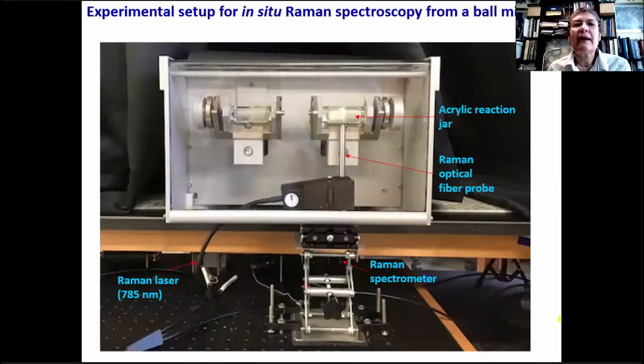So this is a recently received system for in situ Raman spectroscopy monitoring of mechanochemical reactions in a ball mill. So the reactions happen in these acrylic jars, which are shown there, and there is an optical fiber probe which goes directly underneath the reaction mixture while it is ball milled. So the system also has a Raman laser, the one that we have is 785 nanometers. And there is also a Raman spectrometer, and all of this is connected to a computer for measurements.